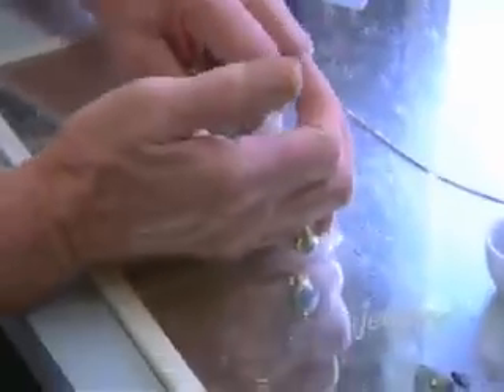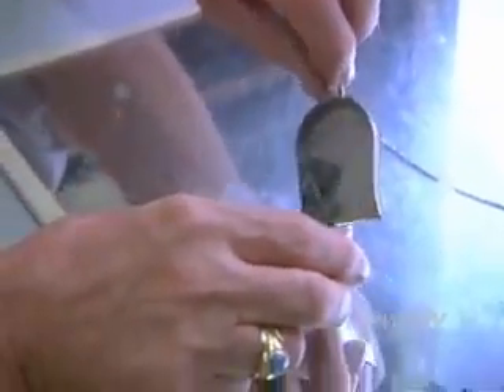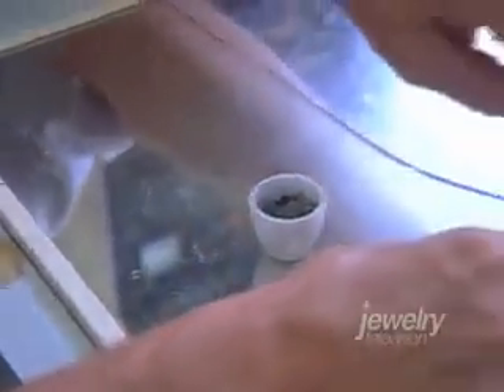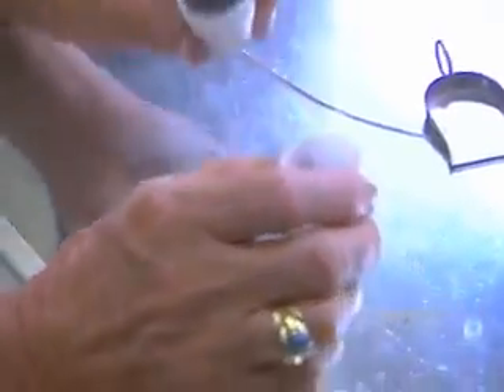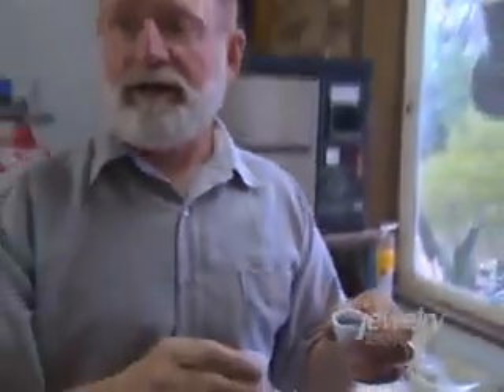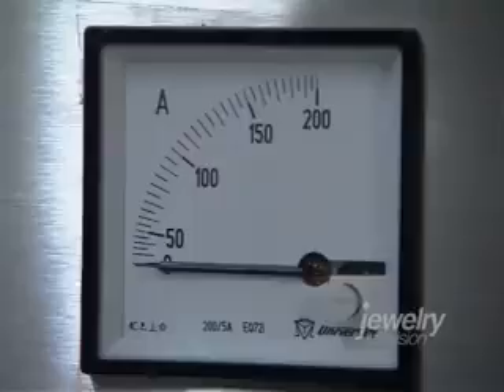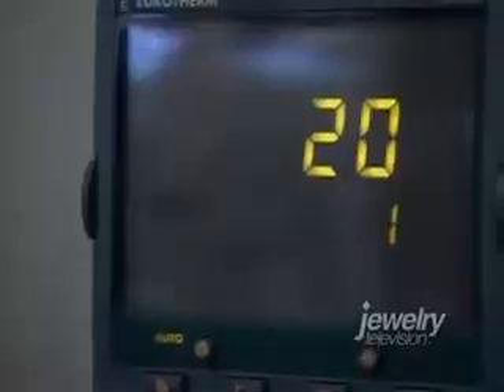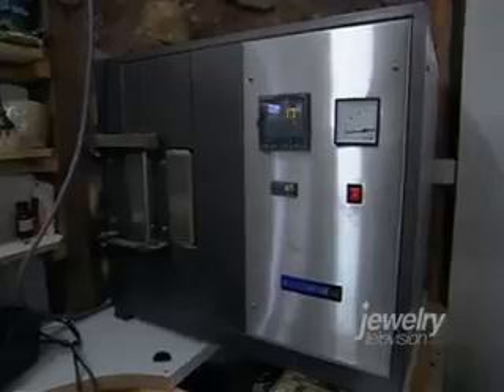We put them in a little sapphire crucible or corundum crucible. And then they go into the oven, which is a heat treating process that goes up to 1400 to 1600 degrees Celsius over an 8-hour period. So they reach the maximum temperature for maybe an hour and they cool down. So it's an overnight process in the oven. A special computer program controls internal temperatures inside the oven. If the critical temperature is not maintained during the heating process, the sapphires can crack.